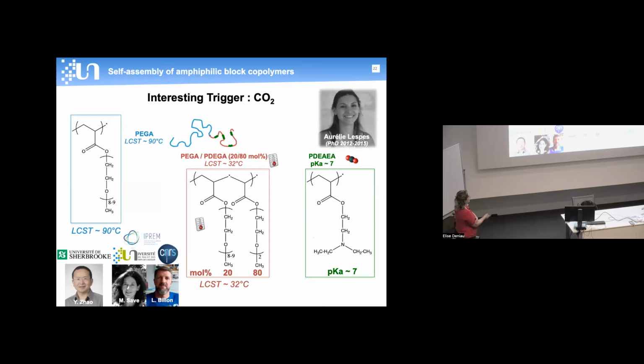So then we develop, together with the PhD of Aurélie Lespès, another pH and thermoresponsive system. And this was in collaboration with Maud Save and Laurent Billon in Pau and Yu Zhao in Sherbrooke University. And in this case, hydrophilic units in blue are the polyethylene glycol acrylate. And the hydrophobic block is composed of 3 different units: